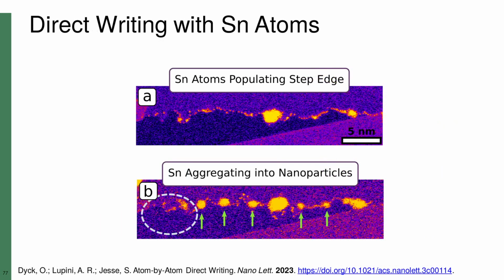Since we have independent control over the substrate temperature, we can change it on the fly. The initial deposition was performed with the substrate held at 500 degrees Celsius. I was quite curious to see what would happen to the deposited tin if the temperature was increased, so I heated it to 900 degrees and then acquired these images. First, we see highly mobile tin atoms decorating the step edges. A few minutes later, we see that tin nanoparticles have formed.